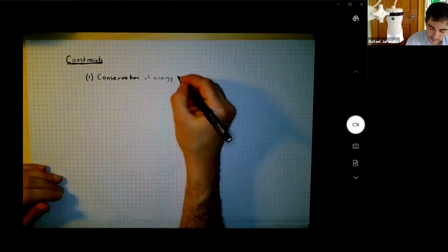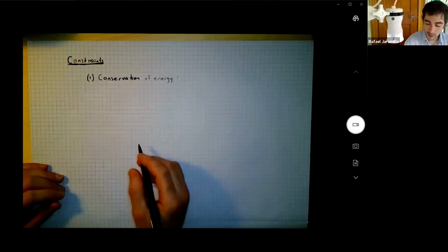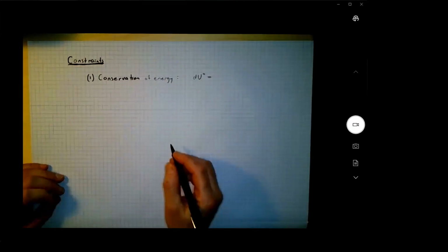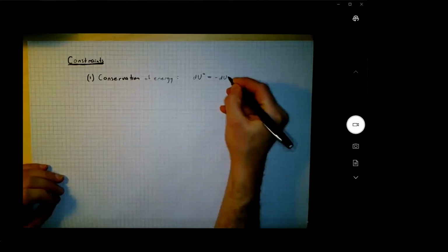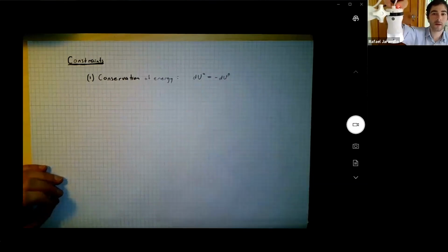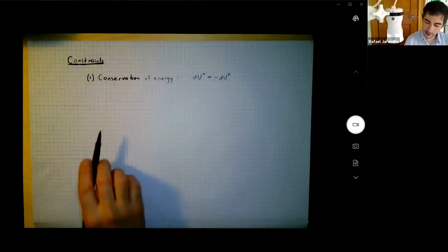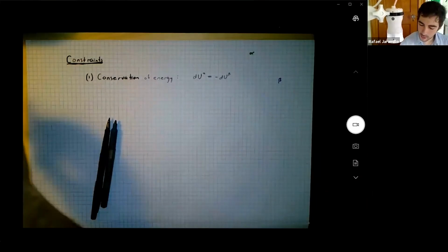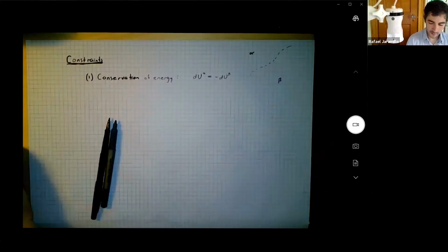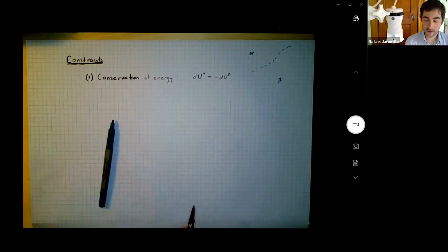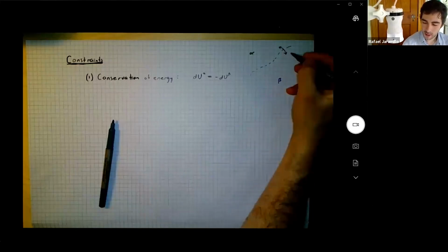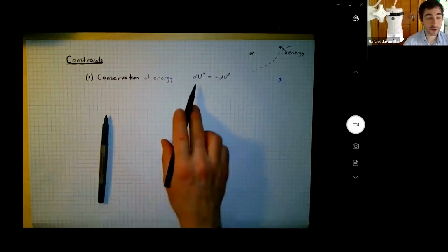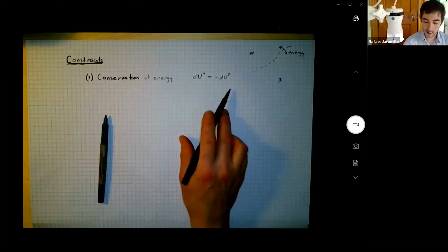Conservation of energy. So conservation of energy, this is an isolated system. So what can we say about du of alpha? If alpha gains energy, where does it have to come from? From beta. So du of alpha has to equal minus du of beta. Again, coming back to our picture, we have an alpha phase. We have a beta phase. They're separated by a very porous, almost non-material boundary. And that boundary allows energy to pass back and forth, right? They can do work on each other and they can heat each other. Okay, that's good. This reduces our number of dimensions by 1, right? We have an additional equation. There's another constraint.